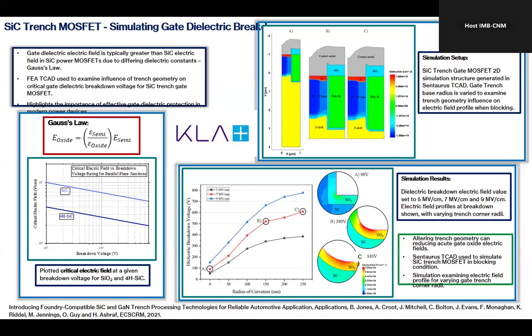Okay, and it's a curse because of this simple Gauss's law, in that the electric field transferred into the oxide is a product of the dielectric ratio between the semiconductor and the oxide multiplied by the high field in the semiconductor, right? So this field in silicon carbide is an order of magnitude higher than in silicon. So that means the oxide is also exposed to much higher fields. This number is about 2.5, about 3 times. So if you're operating at close to 3 megavolts per centimeter in the silicon carbide, the silicon dioxide is operating at 9 megavolts per centimeter, and that's approaching the dielectric strength of the silicon dioxide,